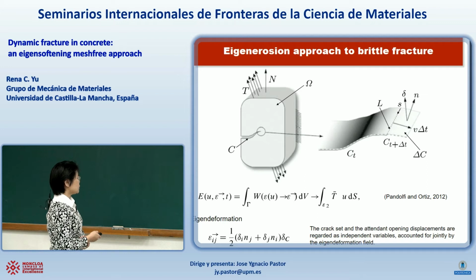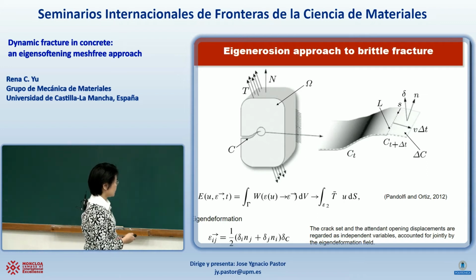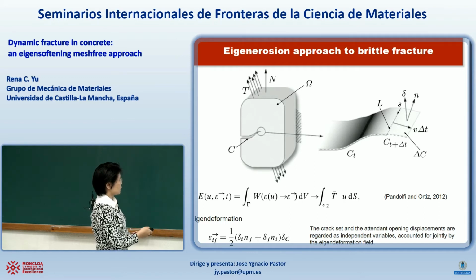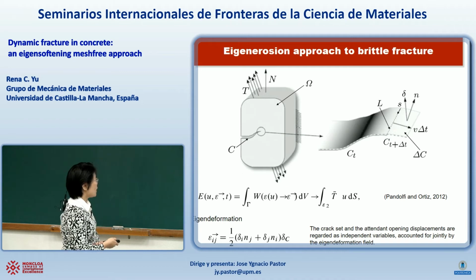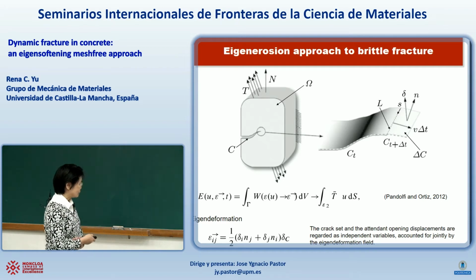The energy functional that is in use is actually this. This is a strain energy function. This will be a minus sign here, this is the traction, and this is the displacement, the external work. The idea behind it is that this strain energy functional is being added with an eigendeformation. The eigendeformation is a mode of deformation that does not cause local energy. So it is defined as, the delta here is the jump between the two crack surfaces, while n is the unit normal here. This is the crack set.